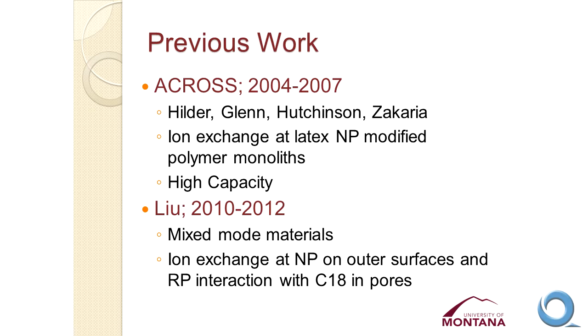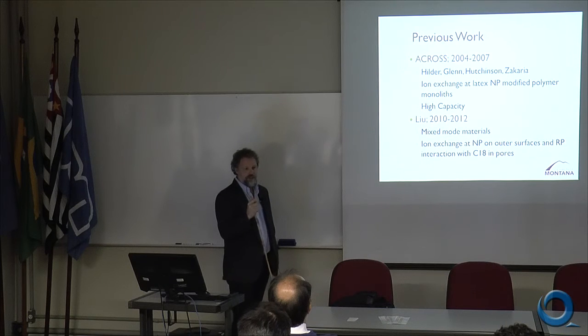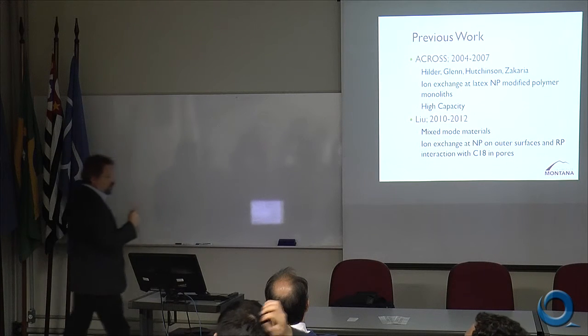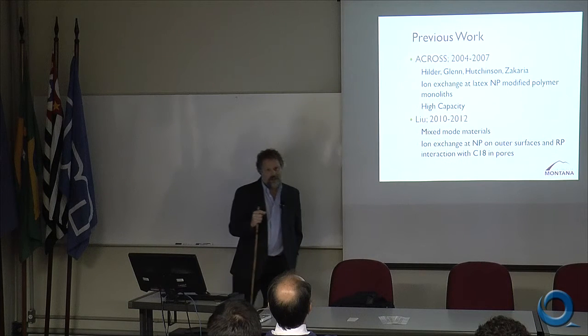We're not the first people to use nanoparticles in separation science, of course, and not the first to think about using nanoparticles to modify a surface. The group at the Australian Centre for Research on Separation Science, ACROSS, in Hobart in Tasmania, multiple authors over a period of 3 or 4 years, they demonstrated that you can take ionic nanoparticles like these, adsorb them to a polymer monolith, and get high capacity, high efficiency separations by ion exchange. So they're ion exchange separations. And this is in fact the chemistry that Dionex uses for most of their high capacity ion exchange materials now. They use a polymer packing material, and they modify it with